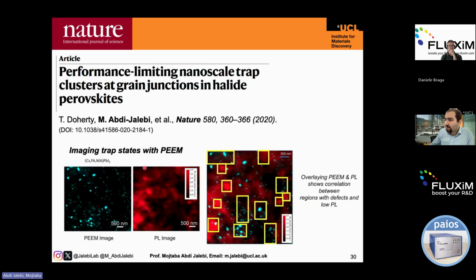In another follow-up work, very briefly, we located the defects within the semiconductor and correlated them with the luminescence efficiency. A good discovery here is where we have the maximum luminescence efficiency. This is a PL map showing the surface of the perovskite, where we have the maximum luminescence, as you can see based on this chart here.